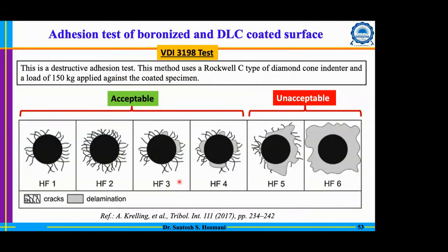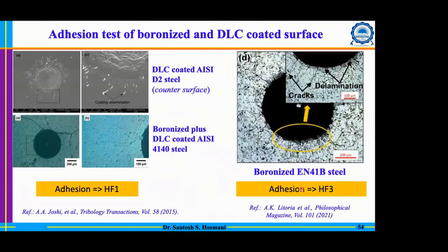And before I go further, I will just quickly give an adhesion test. It is a very simple test, the VDI 3198 test. You can actually determine the adhesion, and there are different scales, mentioned from HF1 to HF6. Generally, HF5 and 6 are not desired. Up to HF4 it is acceptable. And in case of a boronized surface, you can see it is lying on the HF3.